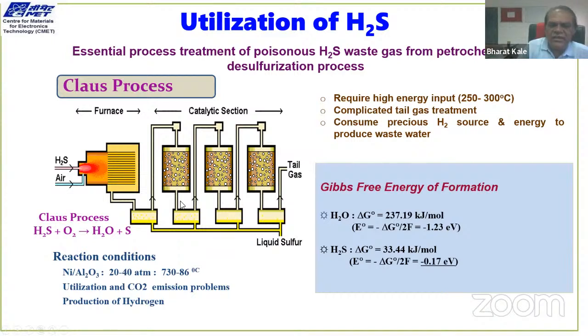But it's again a very energy intensive process. You see that nickel aluminum catalyst at 20 to 40 atmosphere, 730 to 860 degrees centigrade. We are running this reactor. And here also what happens, it's a highly corrosive system, because you get a liquid sulfur. If any sulfur is in contact with the metal and other polymers, it reacts with polymers also. So it's highly corrosive, and so every year we have to have a lot of maintenance for this kind of plants.